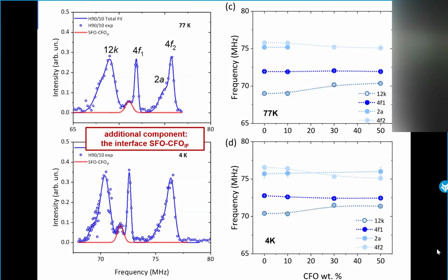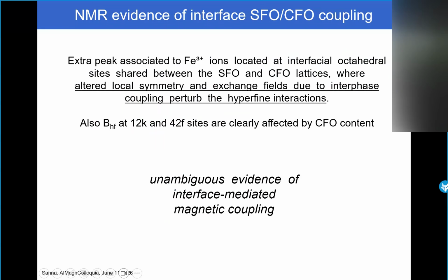But also, as we saw here, other peaks are sensitive to the presence of CFO, which give us an unambiguous evidence of the interface-mediated magnetic coupling, which means that if the two systems are not talking to each other magnetically, then the spectrum should stay constant, the same. But since the spectrum is changing, and in a gradual way, when we increase the CFO content, it means that there is an effective coupling between the two layers.